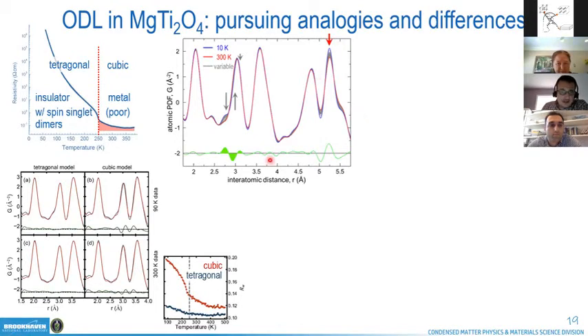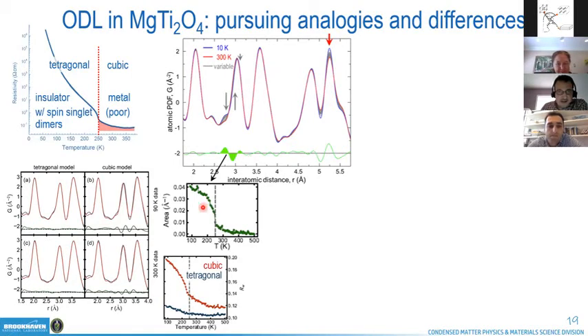You can interrogate this difference curve and integrate it, and what you see is a gradual decrease in the integrated intensity in this feature until it abruptly drops at the transition, and then it continues. In this particular case, the 500 Kelvin data set was used as a reference to generate the differences between all the other data sets and then generate this curve.